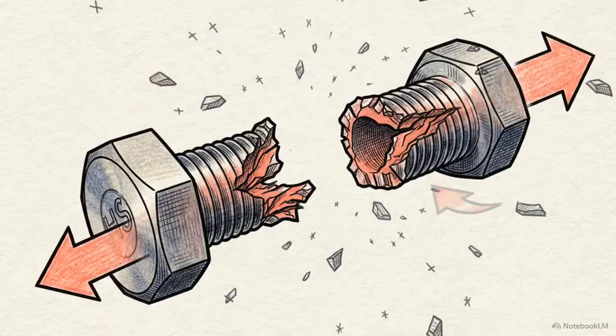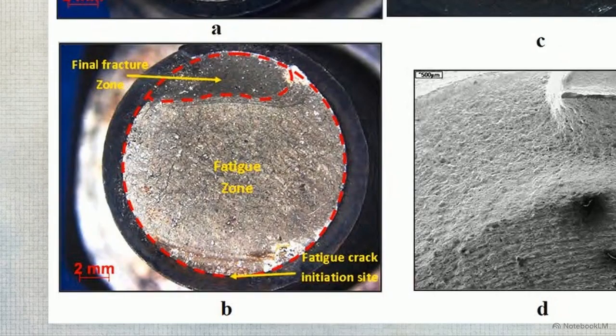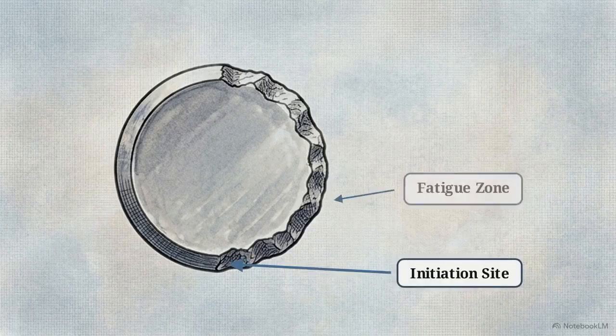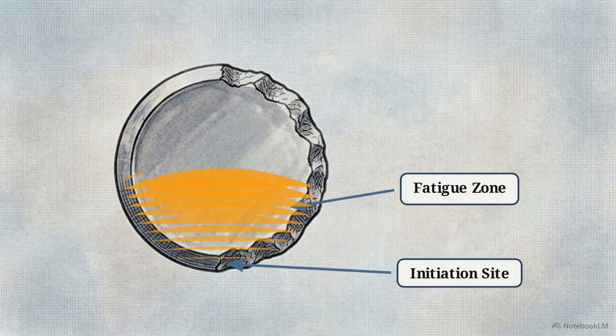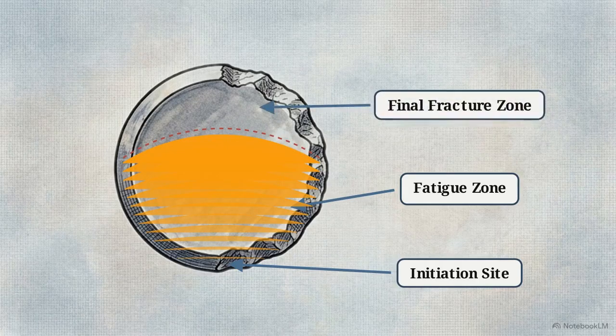overwhelmingly mechanical. Looking directly at the macroscopic fracture surface of one of the broken bolts, the dashed red line separates 2 distinct topographies, a relatively smooth, flat fatigue zone and a rough, granular region of final, sudden rupture. The presence of a fatigue zone, marked by the band of coarse striations mapping the direction of crack propagation, identifies the exact failure mechanism. This is a premature, high-stress fatigue fracture.